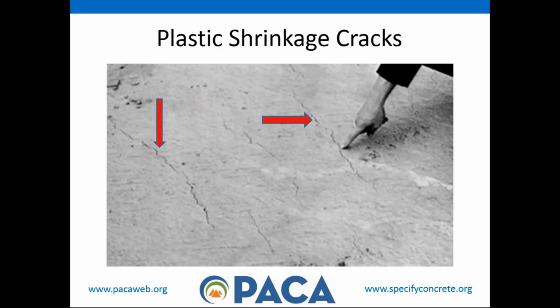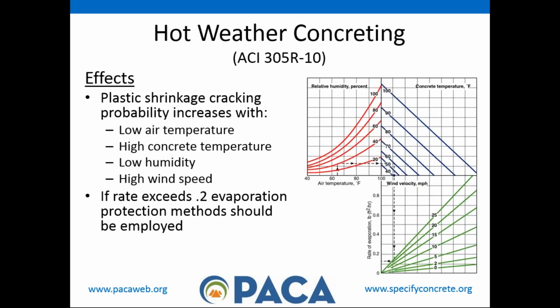Please, when you see plastic shrinkage cracking, the picture I'm going to show you next, don't confuse this with delamination. Delamination is a completely different thing. There's a picture I'm sure everybody's seen time and time again of plastic shrinkage cracking, and nothing can be done about it. Some finishers will try to get back on the slab and get it sealed up or healed up, and that's where delamination occurs, because they're putting water on the surface or trying to scrub some grout into it. Basically, by the time the bleed water works its way through, the damage is already done.